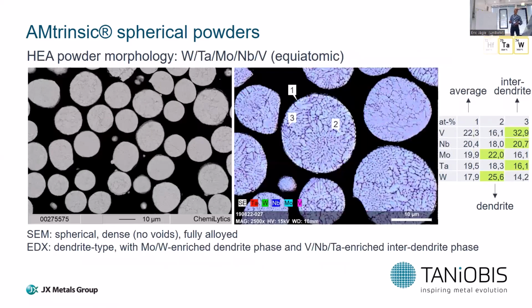Going to a really high entropy alloy, this is, for example, tungsten, tantalum, molybdenum, niobium, vanadium, equiatomic, so each 20 atom%. You can see again very nice and dense spherical particles, and again these dendrite type features. And again, the dendrite phase is composed of the high melting elements here, molybdenum and tungsten, so the group 6 elements. And the interdendrite phase is enriched in vanadium, niobium, and tantalum, so group 5 elements.